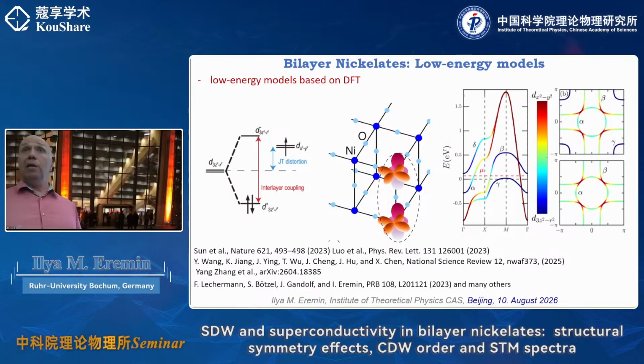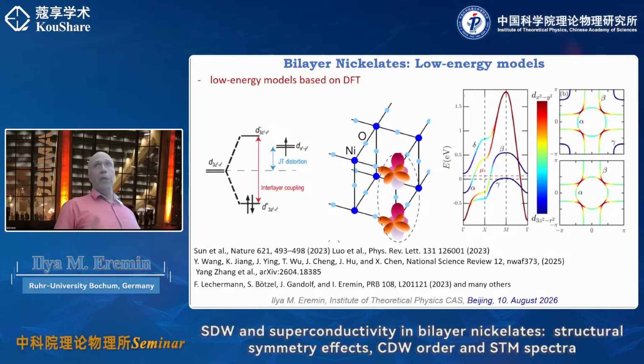The variety of the models that you have currently on the market. So essentially, what is important, I think the conclusion, is that you have to work in a situation where the dz² is much more correlated than the dx²-y², independent of whether you take one extreme view where dz² is completely localized, or even if you think it is itinerant, but it's still closer to half filling, so it's more correlated. Okay, so that's a model.